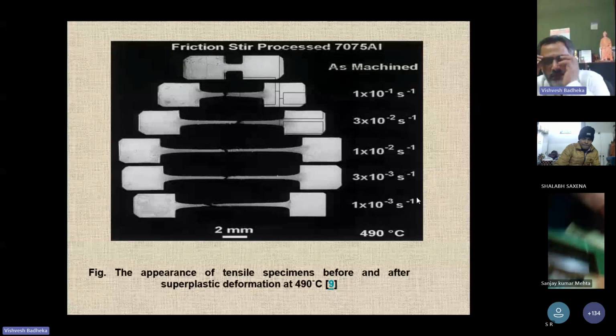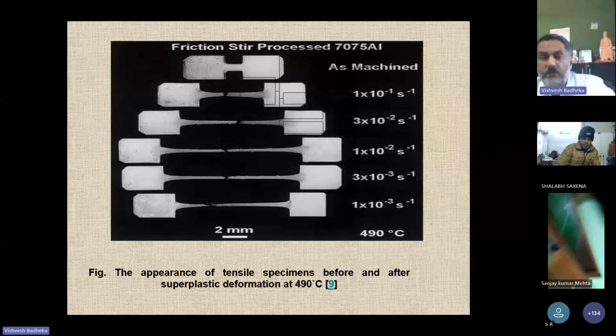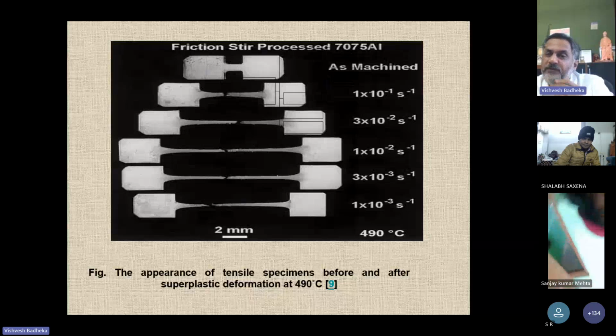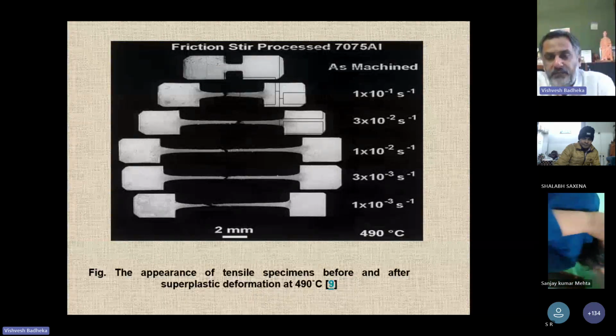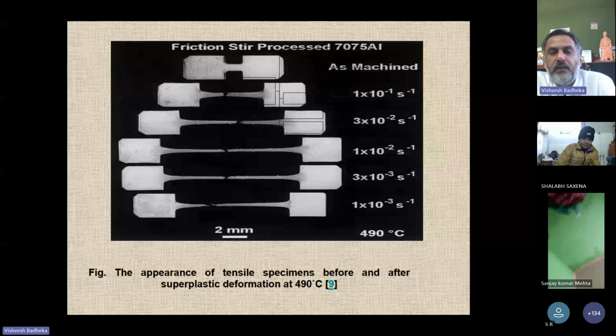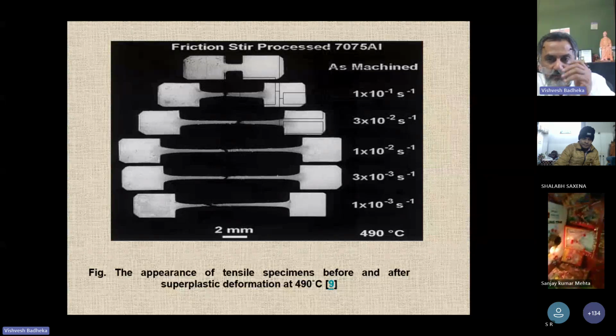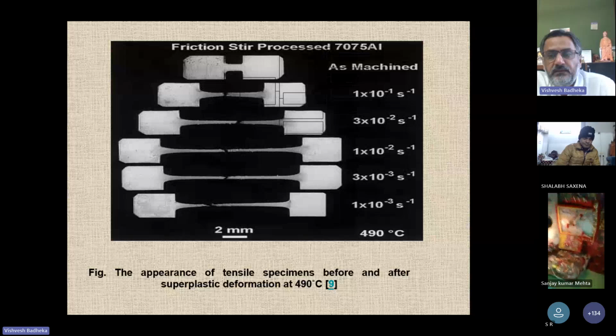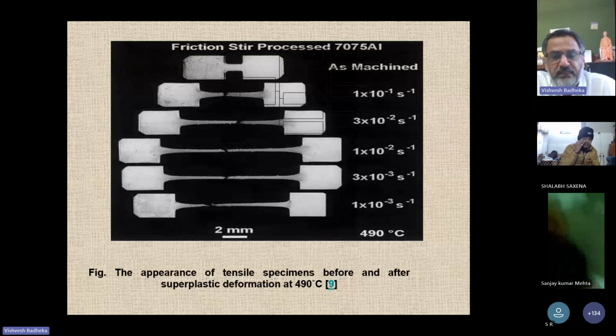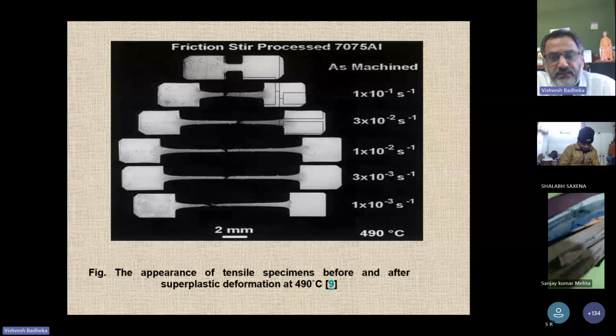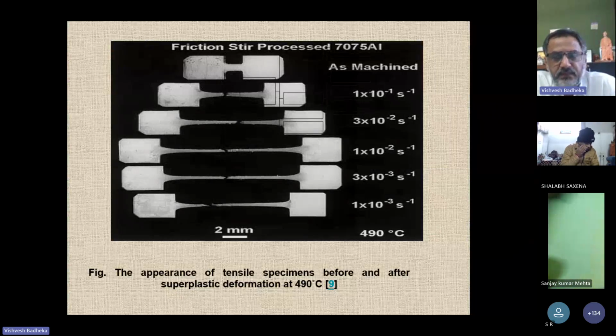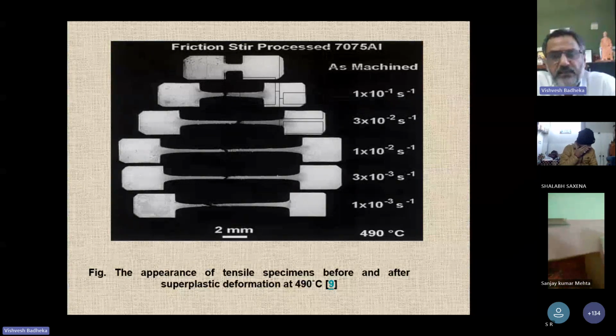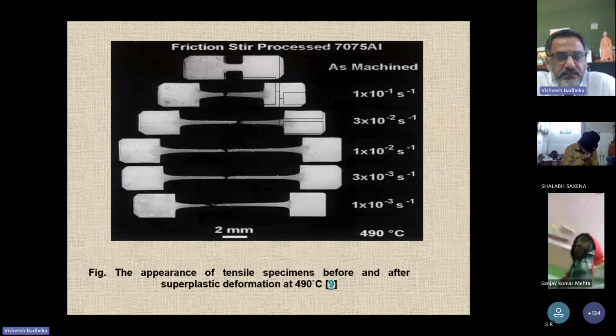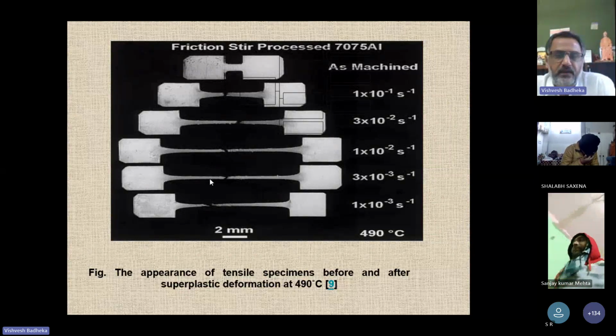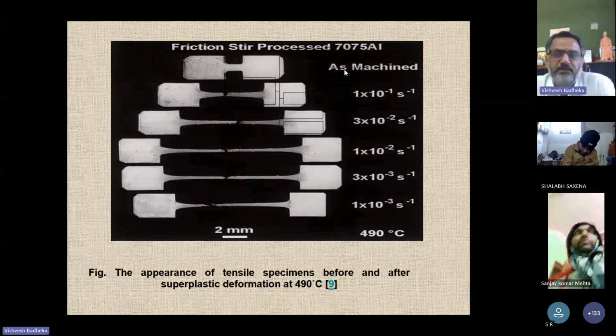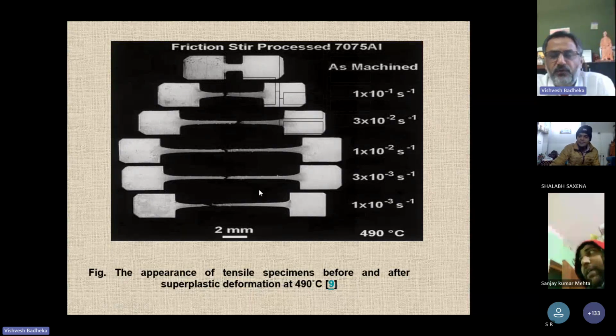Now you see some of the actual pictures of, say, for example, 7075 material, which you can see here, which is as machined. That means no processing has been done. And then after friction stir processing, you can see at certain strain rates and at a fixed temperature of 490 degrees centigrade, the temperature is fixed, you can see the strain rate is getting changed, 1 into 10 raised to minus 1, 3 into 10 raised to minus 2, and so on. And you can see here you are getting a very high degree of elongation after friction stir process. So this behavior that you are observing,